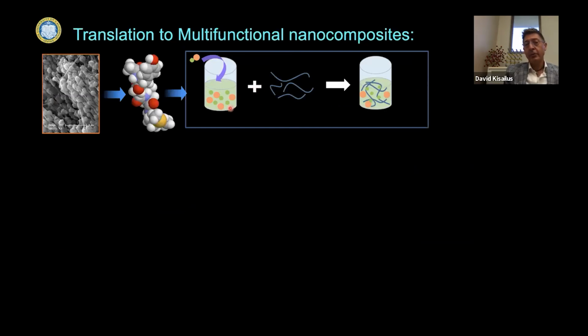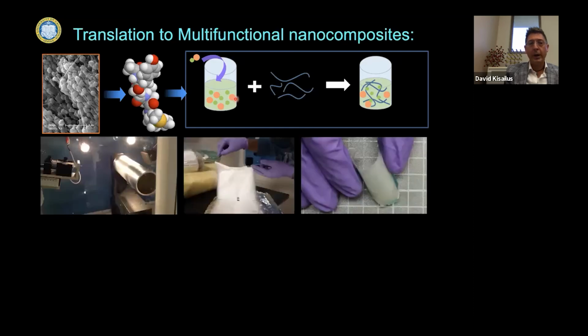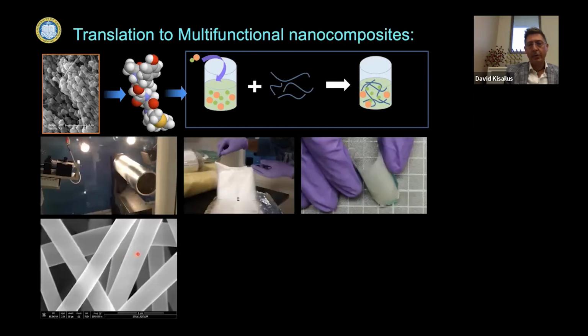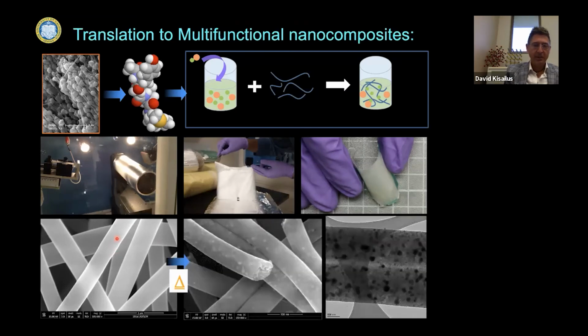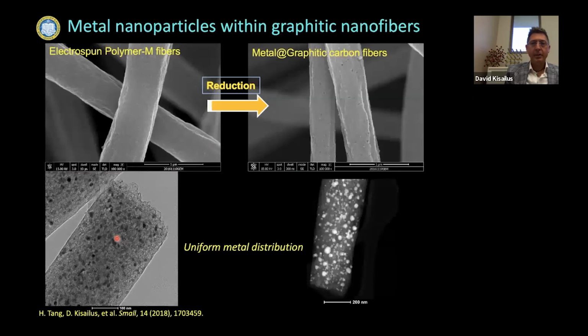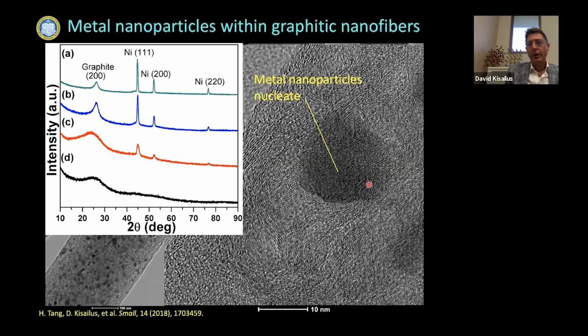So Stephen was trying to infiltrate some iron precursor around these electrospun nanofibers. But in fact, the precursor that we used infiltrated the polymer itself. And I said, well, let's do something with this. So Stephen subsequently heated these fibers under certain conditions, some reducing conditions, and the iron mineral, and now we're using nickel and cobalt as well, subsequently diffused through the polymer carbon matrix during annealing and nucleated as nanoparticles, metal nanoparticles within this carbon scaffold. So what could we do with this? And here you can actually see, for example, this is nickel, single crystal nickel nanoparticles that have nucleated within the carbon scaffold.